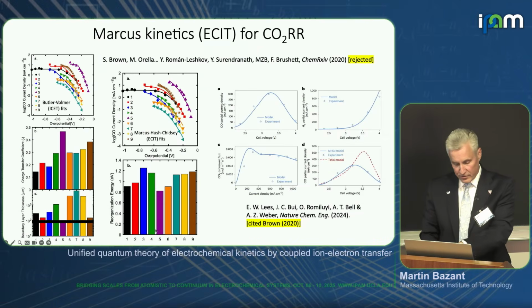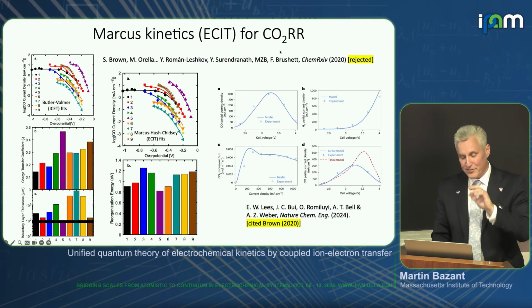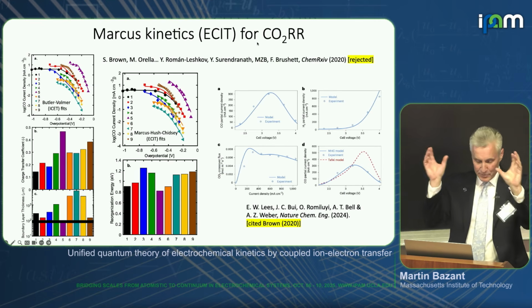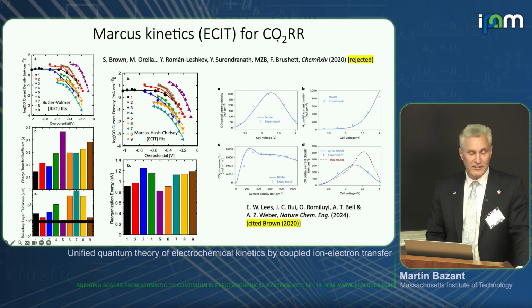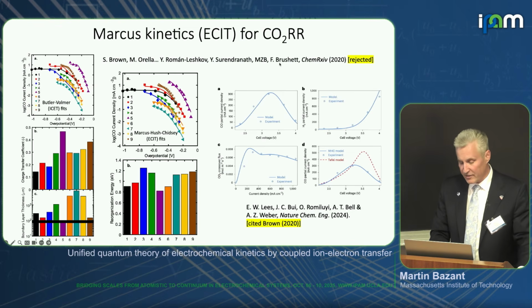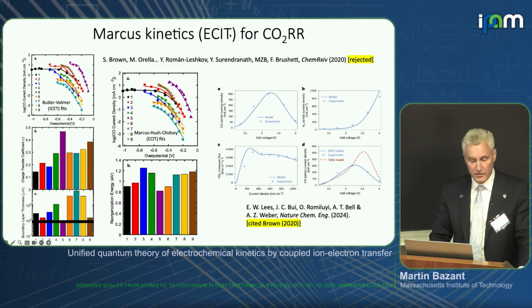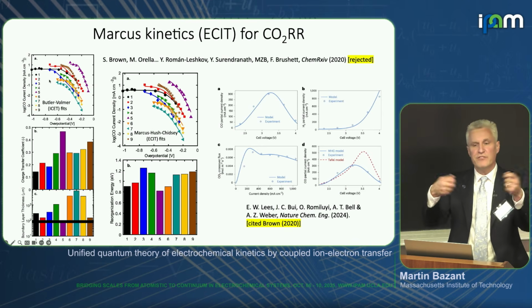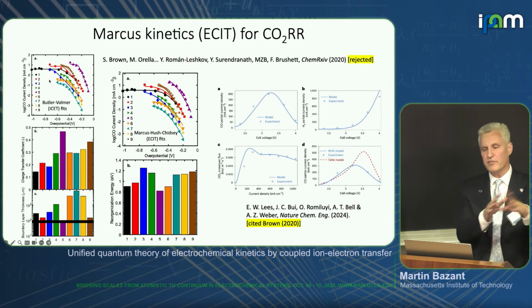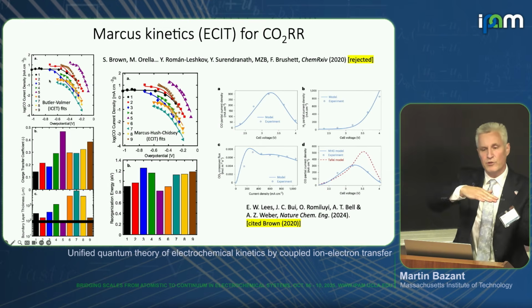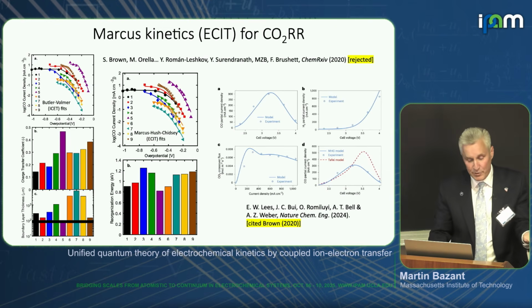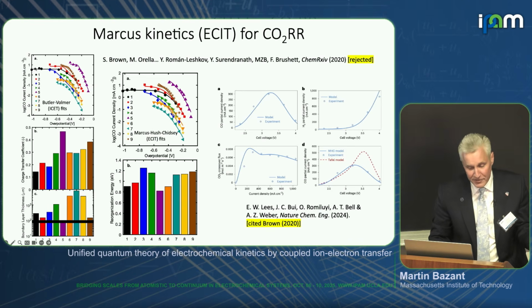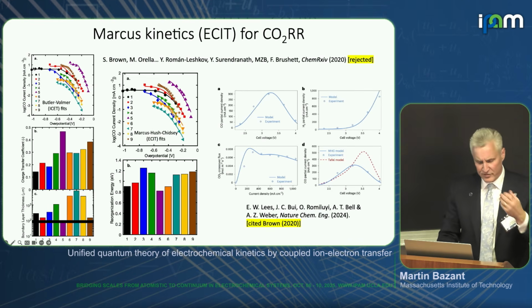One last thing, I'll just show you real quick, this is kind of interesting. In batteries, people have kind of accepted these ideas. In electrocatalysis, it's again starting to be a struggle, but we're learning some interesting things. If you look at Tafel plots for CO2 reduction in water, they look pretty curved, actually, but people always interpret this to say, oh, that's diffusion limitation or some film resistance, and they'll fit that. So essentially what they're doing is keeping Butler-Volmer and straightening it, okay? But the data is pretty flat, and some of the data is extremely flat, which wouldn't happen if you just had a resistor there.